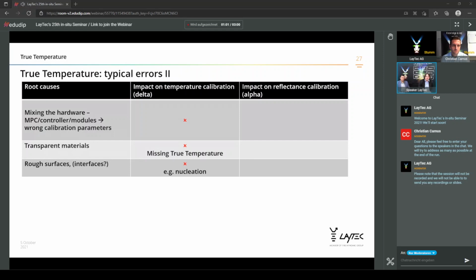Further down, during crystal growth or layer growth, one impact or root cause for a wrong true temperature measurement can be surface properties, like rough surfaces, rough morphology of surfaces, or even of layer interfaces. For example, a rough nucleation layer interface can have an impact on the correct consistency of the true temperature calibration.